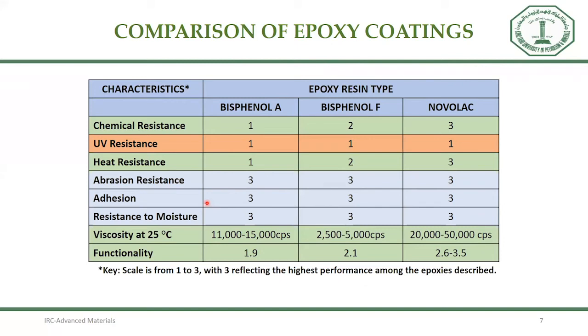So here, this table compares the important properties of the resultant epoxy coatings when we use different kinds of epoxy resins. The scale ranges from 1 to 3, and 3 is the highest performance. When you look at abrasion resistance, adhesion, and resistance to moisture, all the epoxy resins hold the highest place. But when you look at chemical resistance and heat resistance, the Novolac epoxy exhibits the highest performance. It's because of the highest functionality. Here the functionality refers to the number of active sites responsible for the curing reactions. So the higher the functionality, the higher the molecular weight, which can improve the properties related to chemical resistance and heat resistance.